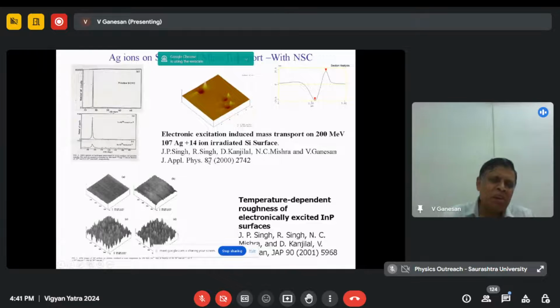And it all happened through a very good scientific interaction between UAC and GUJCOST University, and our students and the Kandila students. It was a very nice interaction that we got. It's also some of the first experimental evidence of so-called swift heavy ion irradiation in India at least, because up to that, people thought that only nuclear collisions can produce all these damages. Electronic energy loss cannot produce it; it will simply go like a bullet, etc. Now we understand that even at 100 MeV and 200 MeV silver, you are able to see material damage to such an extent that you can explain textbook effects like Coulomb explosion or thermal spikes very nicely.